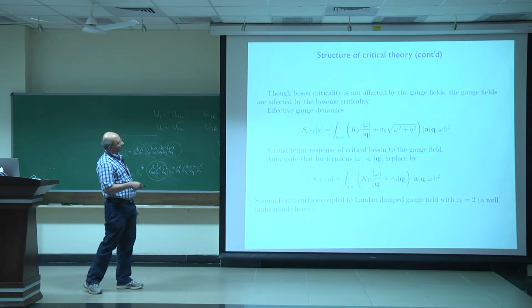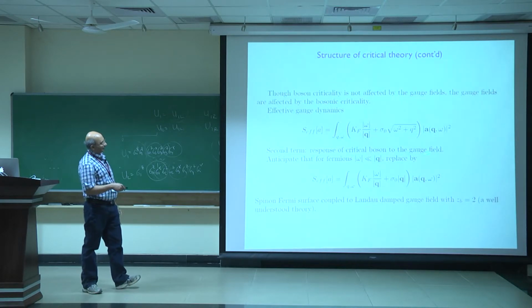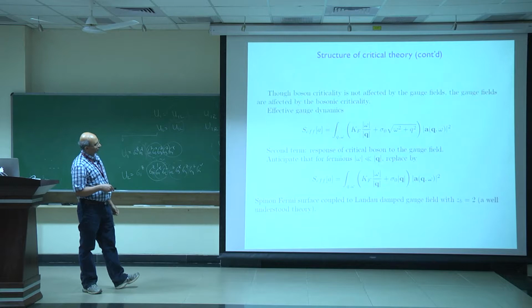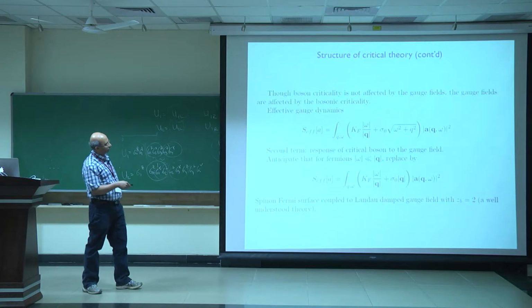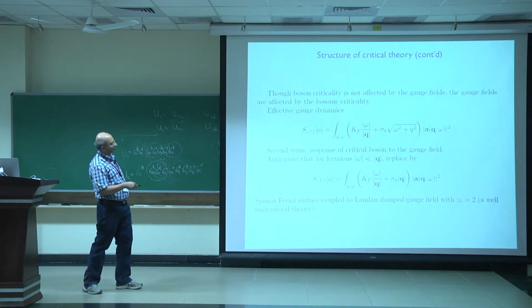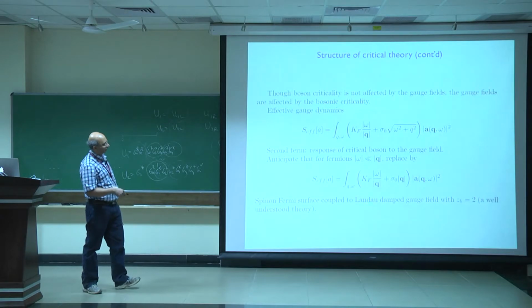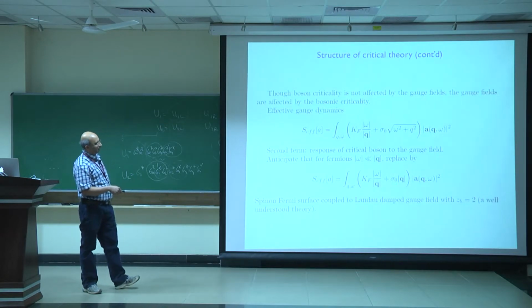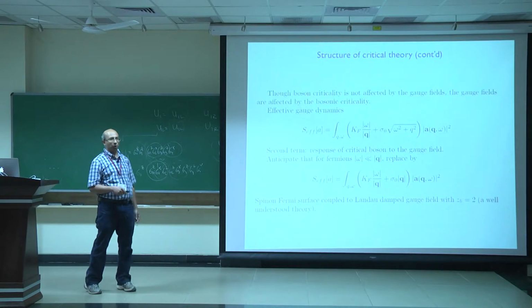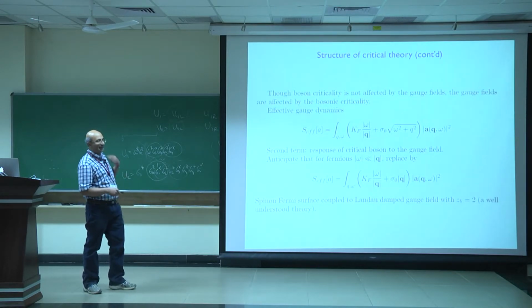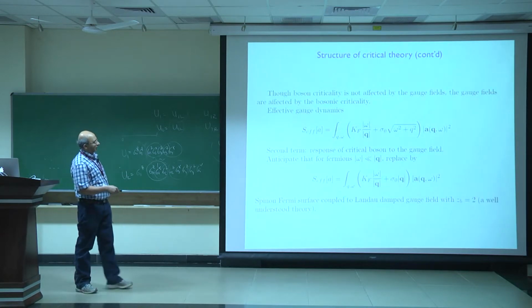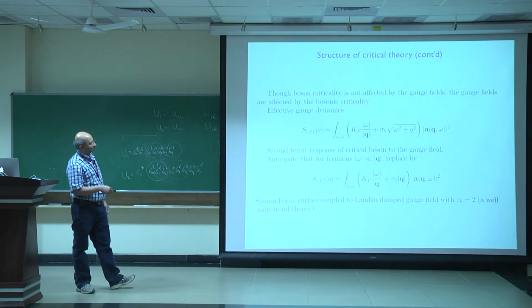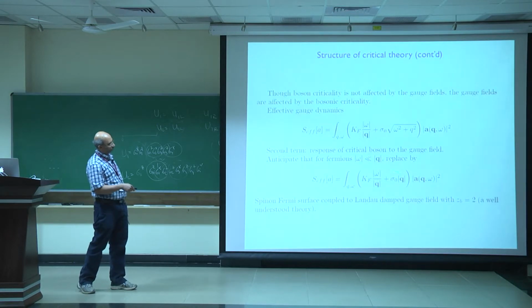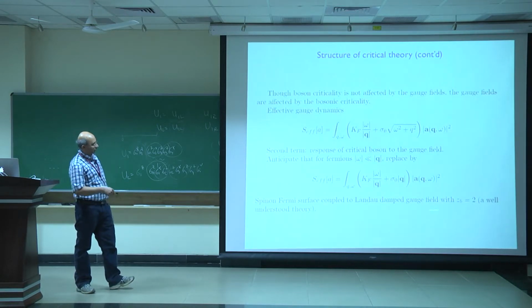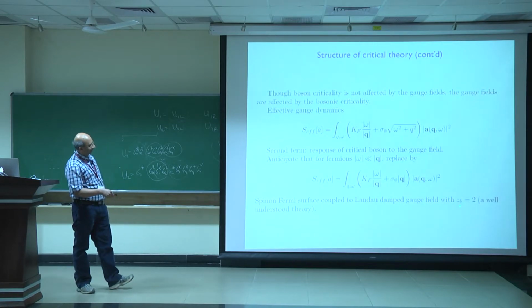So we have some effective action of this kind, and anticipating that as far as the fermions are concerned, the kinematic regime that's relevant is frequency much smaller than q, we can ignore this omega squared in this term and end up with this effective action for the gauge field, which is modified from what it would have been had the bosons not been critical. Had the bosons not been critical, this would have been a q squared, analytic in q. Right? Now, with this form of the gauge dynamics, the typical frequency scale for the gauge field is of order q squared. So this is what we call a Landau-damped gauge field with a dynamical exponent of 2.